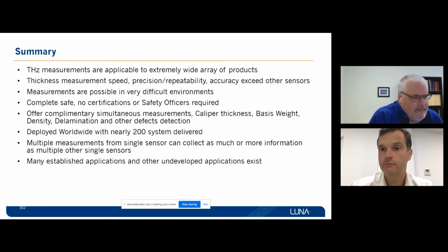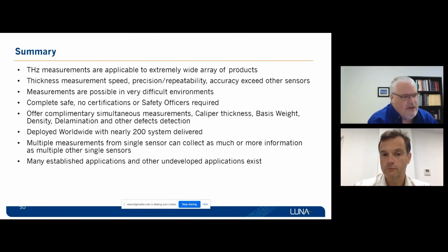Because it's a time of flight measurement, unless the curvature is extremely sharp, something like a radius of curvature of a centimeter, which is rare but not unheard of, and we have ways of dealing with that too. But generally speaking, if you're looking at complex curved surfaces on the exterior of your aircraft that has many centimeters of radius and curvature, the accuracy on a flat versus that complex curvature, either concave or convex, is exactly the same.